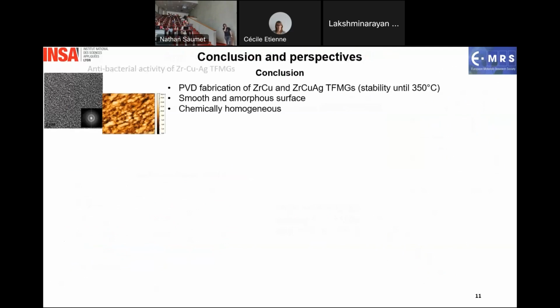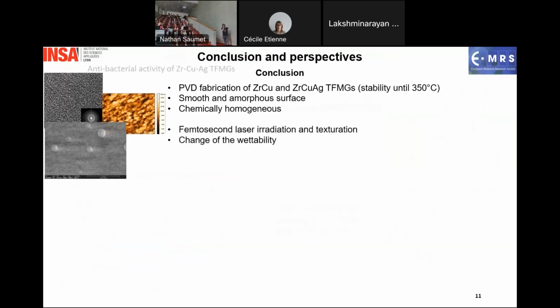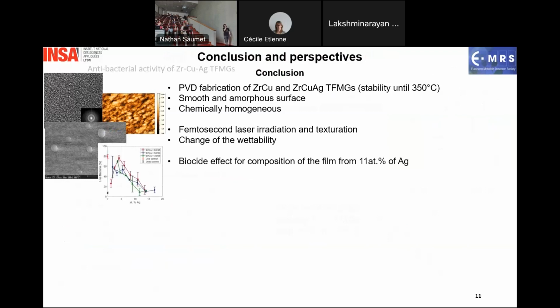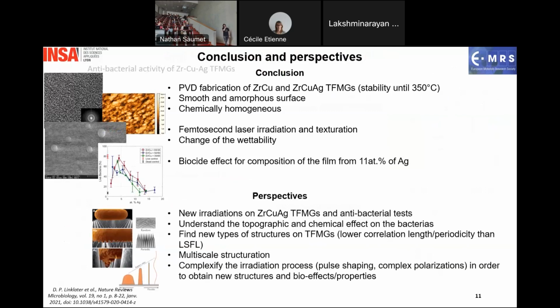So as a conclusion, we made PVD fabrication of zirconium copper and zirconium copper silver thin film metallic glasses, with stability up to 350 degrees. We have smooth amorphous surfaces, and they are chemically homogeneous. We made femtosecond laser irradiation and texturing with a change of wettability checked at the microscale in environmental SEM, and a biocide effect just due to the chemical effect of the silver in the metallic glasses.